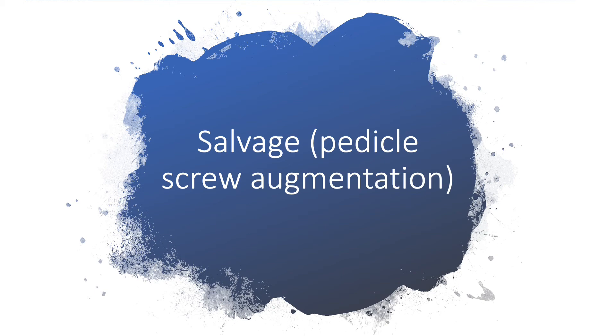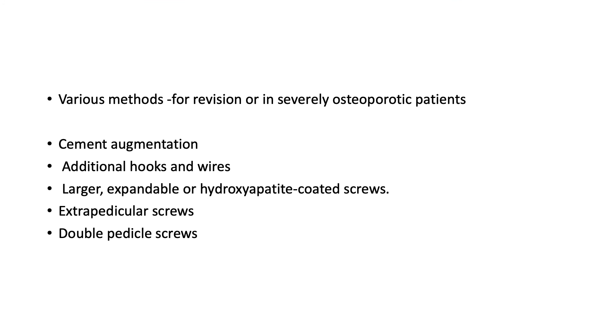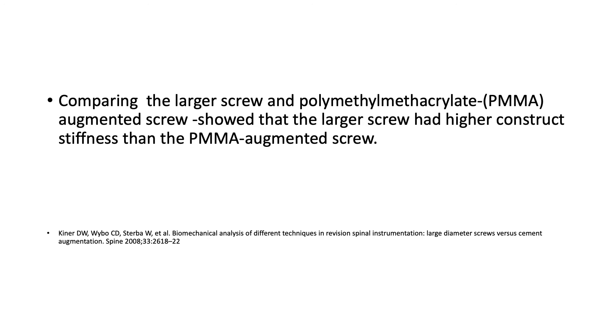Now let's discuss salvage techniques for pedicle screws, or pedicle screw augmentation techniques, used especially in revision surgery or severely osteoporotic patients. The various techniques available include cement augmentation, use of additional hooks and wires, larger expandable screws or hydroxyapatite-coated screws, extra-pedicular screws, or even double pedicle screws. Comparing a larger diameter screw with a polymethyl methacrylate cement-augmented screw showed that the larger screw had higher construct stiffness than the cement-augmented screw.